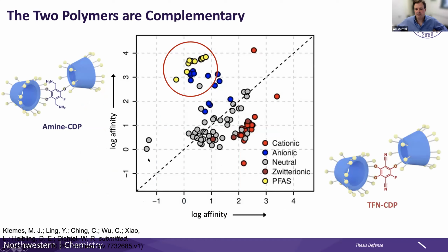So now this is that same kind of box plot that I showed before, where the new materials are on the left, and if you're above diagonal, this now being a log-log plot, as you go to this upper left corner, that's dramatically enhanced selectivity for these anions, and all of those yellow dots are the PFAS compounds. So this is a really good visual to show you that not only did we get a material that combined anions well, we got a really good material for anionic PFAS. And then our original one, you can see the cluster of cations plays out visually here in a slightly different way, but you can still see that's pretty consistent.